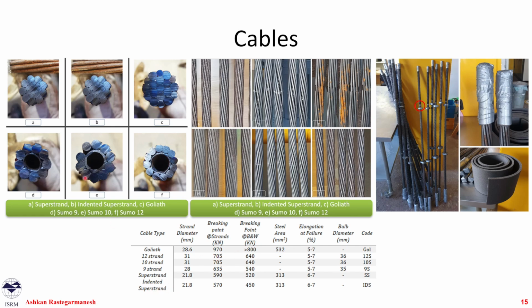So we had 2 smaller cables, which are these 2 cables that we see here. These 2 had around 22 millimeter diameter, and one of them was a plain cable, the other one had indentation, so it was an indented super strand. The name of them was super strand, that's a commercial name. So IDS or SS, that's how we refer to them. The other cable was a 100-ton cable, which is a plain cable, the highest capacity cable at the time, a very big cable, the Goliath cable, or we call it GOL. That's a code that we use for them.